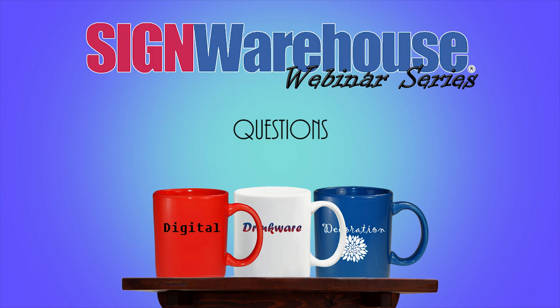And Levon says, so you recommend the Endura vinyl to do plastic and metal tumblers? Yes, the Endura gloss vinyl is very good for that application. The only difference that I've seen in applications with Endura gloss on plastic and metal is that with a brushed finish like you have on a YETI, it's not really a smooth, non-porous surface, and so when you apply the vinyl to the surface, what you want to do is squeeze it very securely and wait about 5 to 10 minutes before you start to remove the transfer tape.